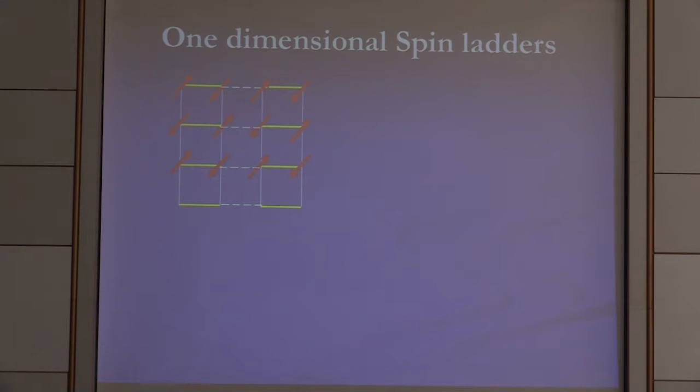Well, for example, if I take the dimers that I was mentioning before, the reason why I focus on dimers rather than isolated spins is a little bit specialized. I don't want to discuss it here, but essentially the dimers have the advantage that for most of the phase diagram, the magnetic moment is relatively small. So parasitic interactions like dipolar forces and so on are much weaker than if you deal with normal spins.